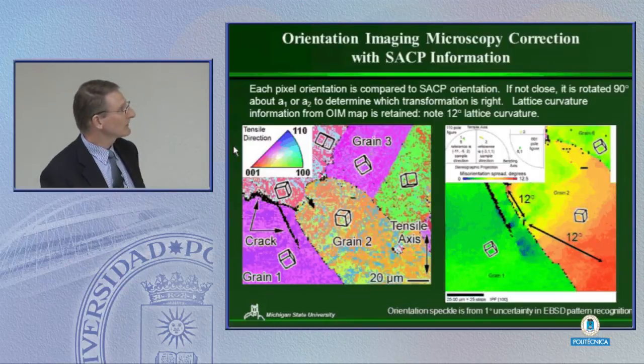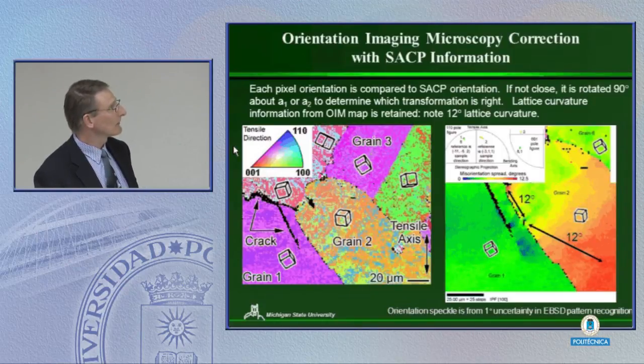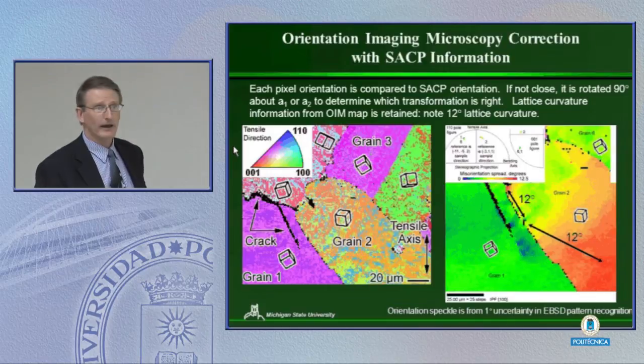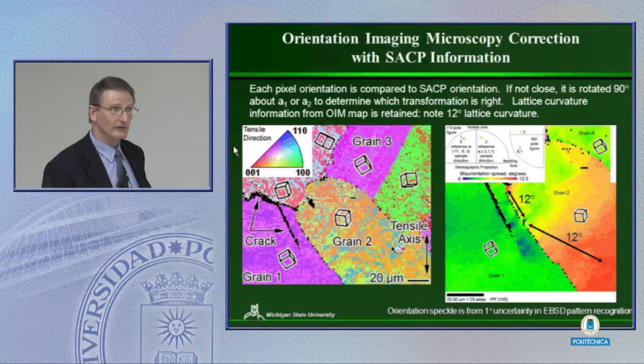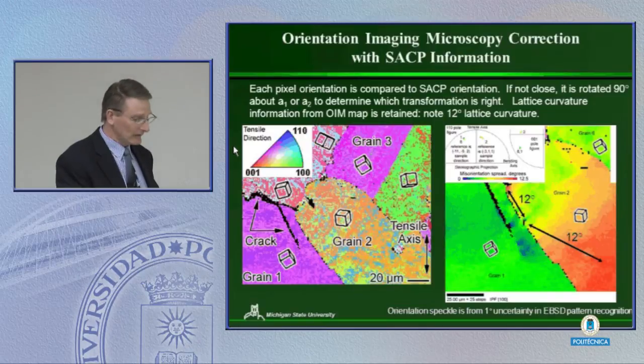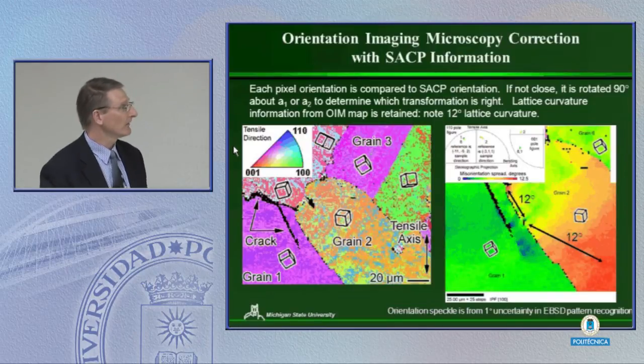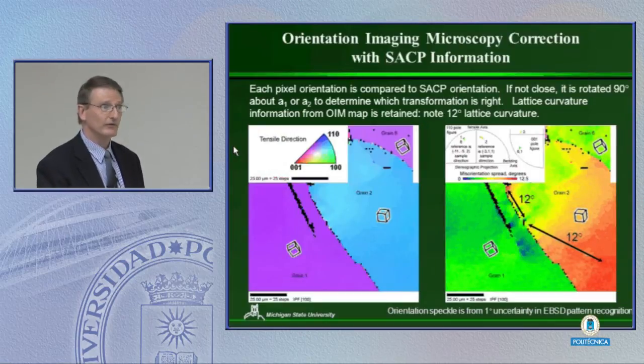Using that, then, we can take this pattern and run a little algorithm to correct these patterns to give us the true orientations. But then what we can do is not only do we know the true orientation of a particular grain, we actually can go back and see the large crystal rotations that are associated with the plastic deformation there. So this is something that EBSD really doesn't allow you to do. We have to supplement the EBSD with selected area channeling.